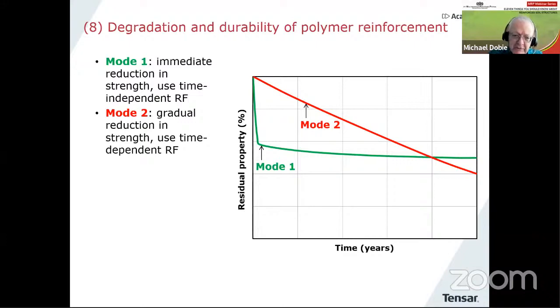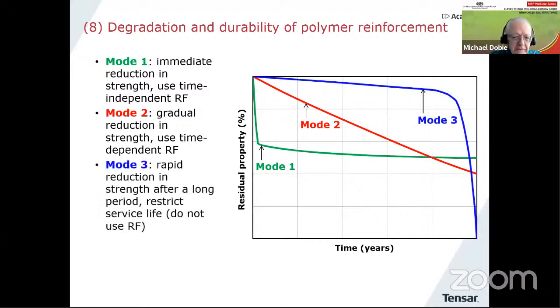In this case, you can determine a reduction factor based on time, and you can put that into your assessment of geogrid long-term strength. And then there is mode 3, in which nothing much happens until you get almost to the end of the design life, and then there's a sudden reduction in strength. In this case, a reduction factor in the normal way doesn't make much sense, but what we have to do is restrict service life to make sure we don't reach that sudden downturn in that particular degradation. So those are very useful concepts.